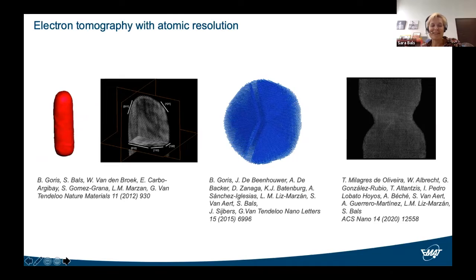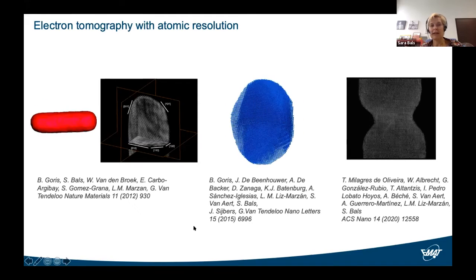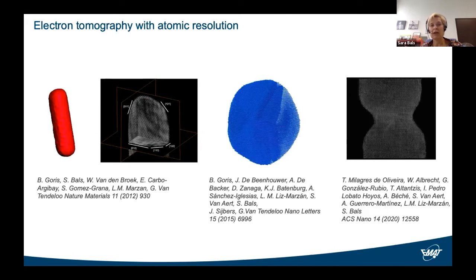model-like systems, such as these gold nanorods, and you can see slices through the 3D reconstruction, and we were able to determine which type of crystallographic facets we had at the surface. Then later on, we were also able to investigate the presence of defects, such as this 5-fold twin in this gold nanoparticle, which contains about 90,000 atoms. And for these two examples, we had to exploit some prior information about the system.